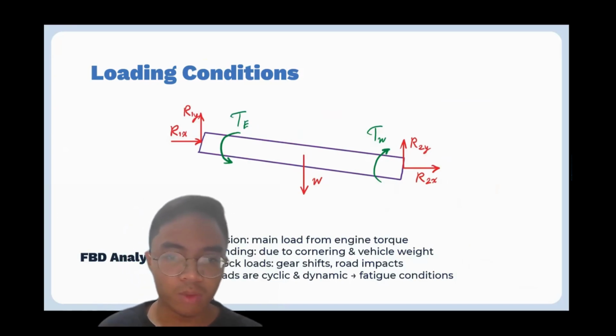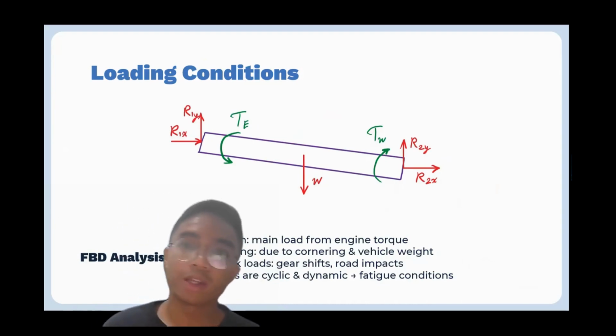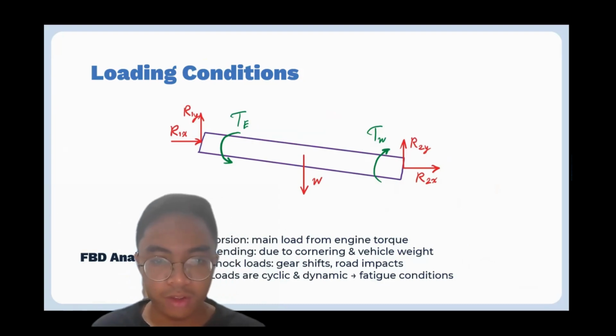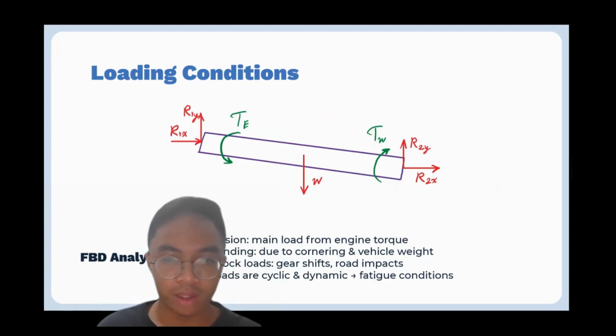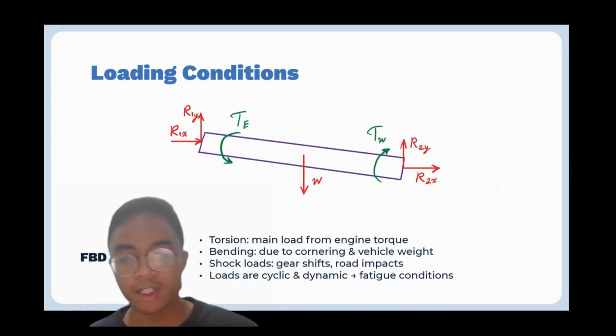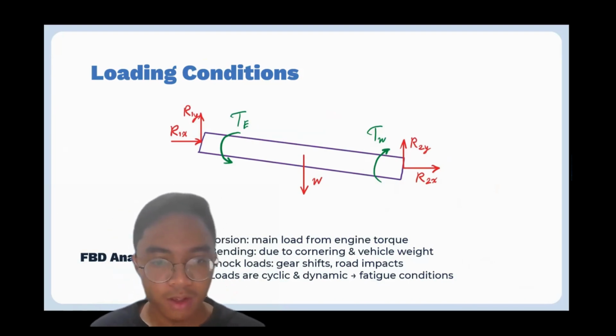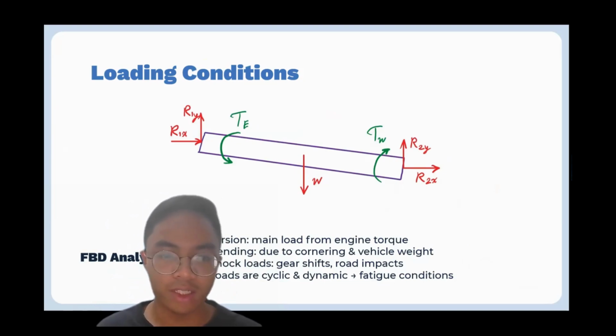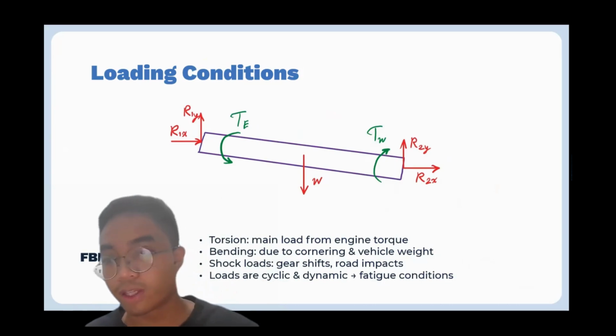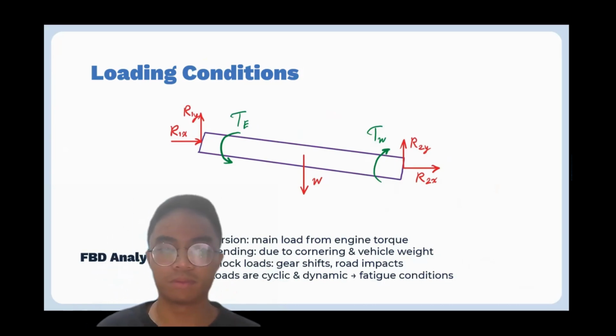So the half shaft was not only carrying torque, it was exposed to a combination of complex loads. The dominant load was torsion, of course, coming from the transmission of engine torque. On top of that, bending stress acted during cornering and from the vehicle's own weight. And finally, shock loads appear during aggressive gear shifts or road impacts. These loads were not static, they were cyclic and constantly changing. The cyclic torsional and bending stress create the perfect condition for fatigue to develop over time.